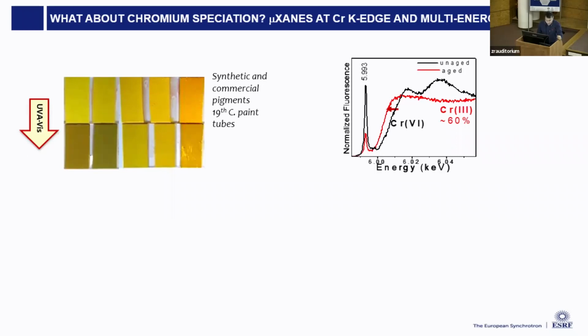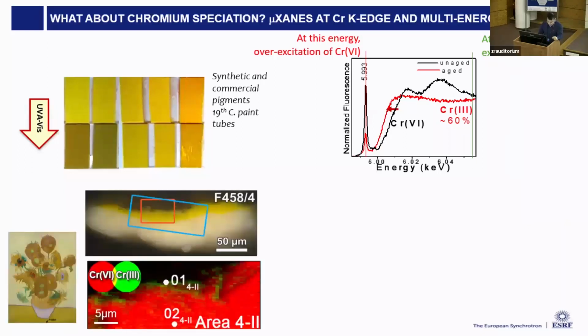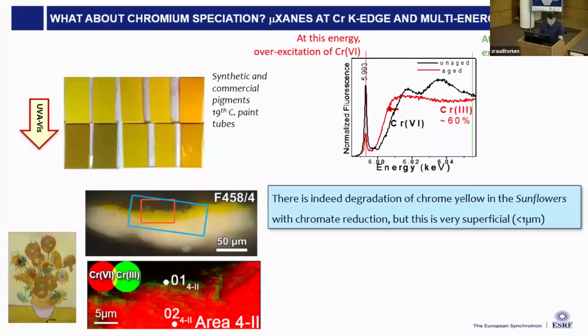The next question is, how deep is such a degradation? To answer this, we exploit the fact that if we excite fluorescence map at this energy, we overexcite chromate. While if we are far above the edge, we excite all types of chromium, independently of its speciation. The signature has been exploited to produce these two energy maps, which show that in the sunflower fragments, there is indeed degradation, but which is extremely superficial, less than 1 micron. This example shows the interest of ID21 for such scientific cases, but also shows that we are at the limit of the spatial resolution. And that results are based on only 2 energies, which is pretty qualitative. And we may miss the presence of other species under this assumption.